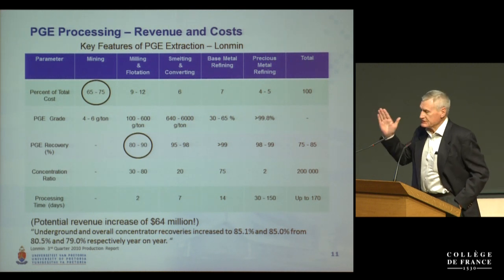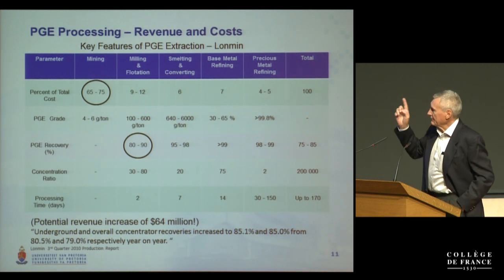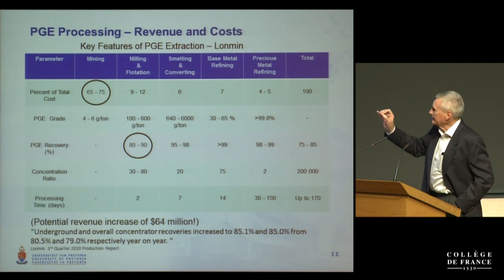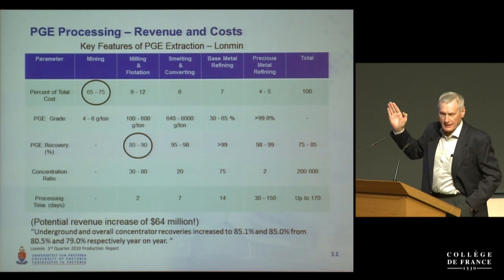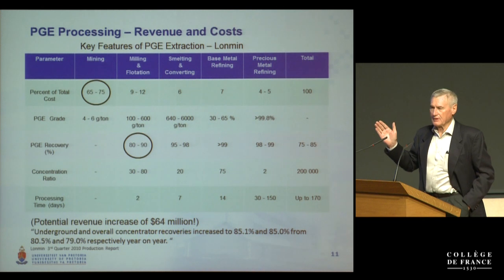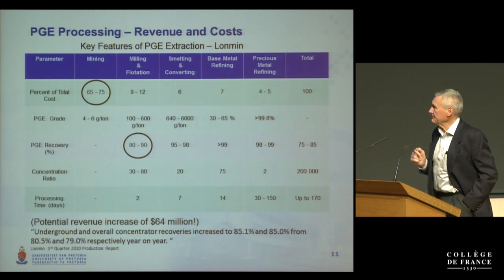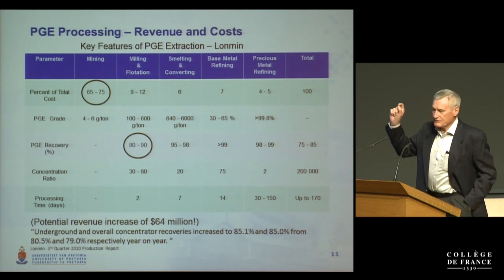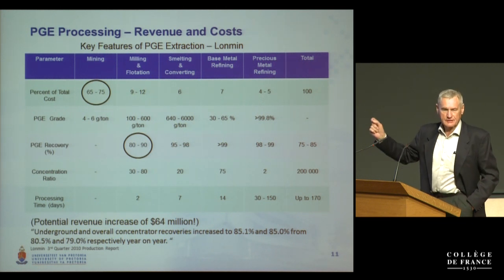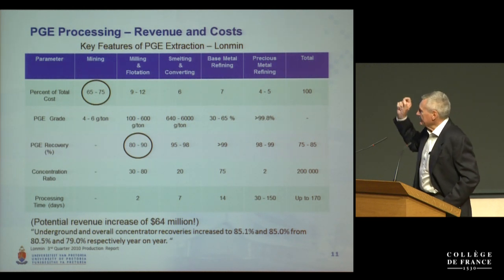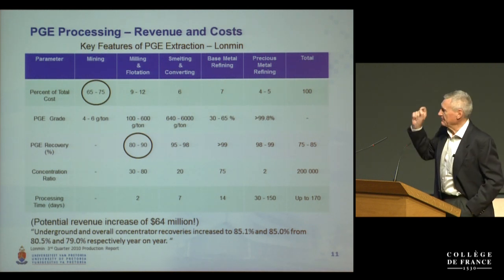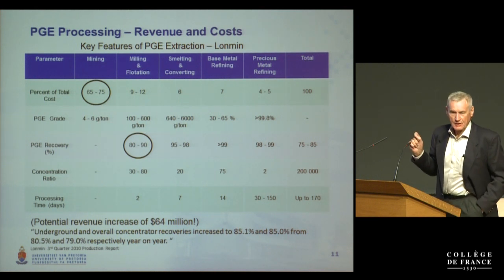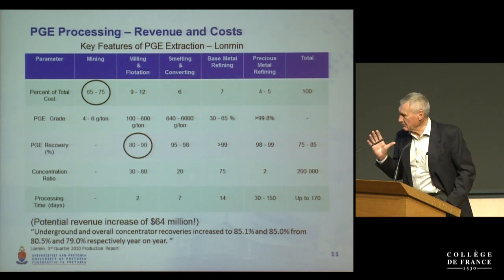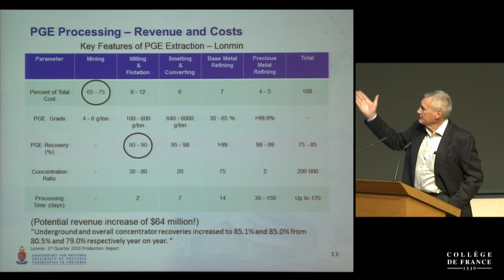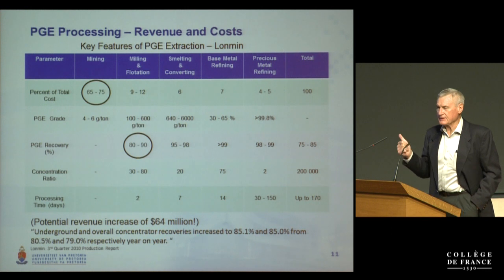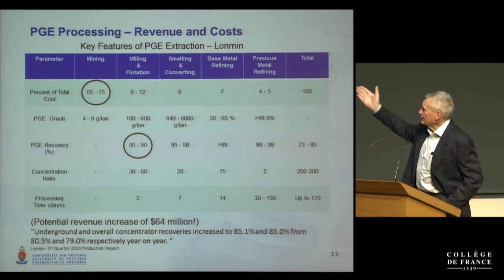You also see here the different stages in the extraction of platinum group elements. You have the mining, you have milling and flotation, smelting and converting, base metal refining, which means the removal of nickel and copper, and then precious metal refining, where you get the pure precious metals such as platinum, palladium, rhodium, etc. What I highlighted here, in terms of the total cost, mining is by far the predominant contributor to cost. In terms of revenue, milling and flotation is by far the biggest contributor to an increase in recovery. So if one wants to look at a decrease in cost, you would concentrate on mining. If one would concentrate on increase in revenue, you would concentrate on milling and flotation and not on the other downstream processes.